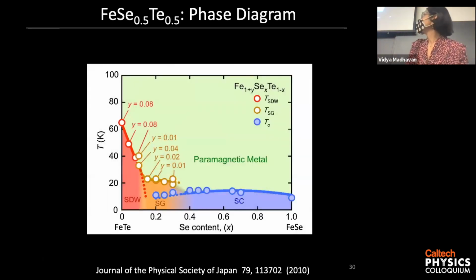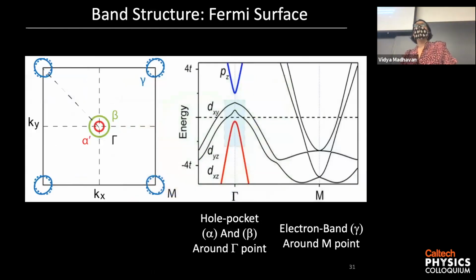So this is the phase diagram of this material, and the actual composition we are interested in is right in the middle, which is 50% selenium and 50% tellurium. This is just for the experts. I just wanted to show the band structure. There are many different pockets, electron and hole pockets inside the Brillouin zone. And actually, each of these becomes superconducting with a different gap magnitude. And so you'll see that when I show you the STM spectra.